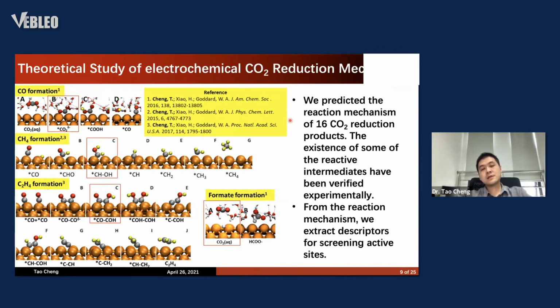So for the CO2 reduction, the problem is that the current catalysts have low activity and the selectivity is also low. So to improve the performance of the catalysts, we need to understand the reaction mechanism well. Experimentally it is extremely difficult, because the reactive intermediates are really small, at the atomic level. So this is one challenge. Another challenge is that the reactive intermediates are usually very short-lived. But this is not a problem for our simulation.